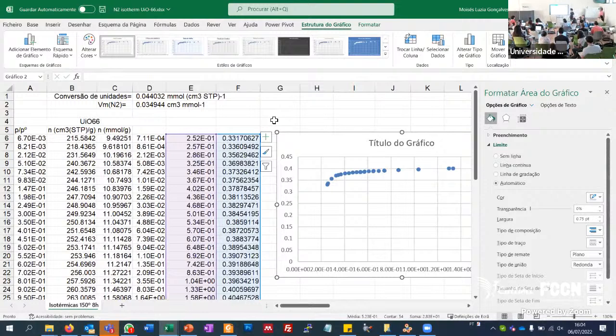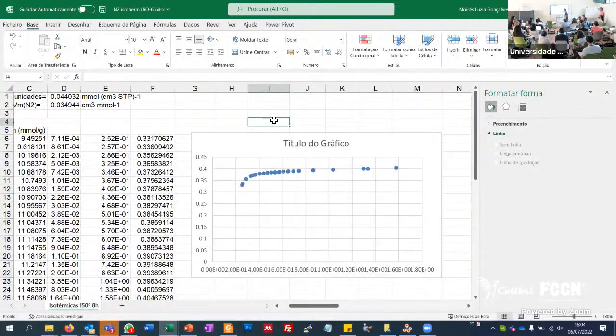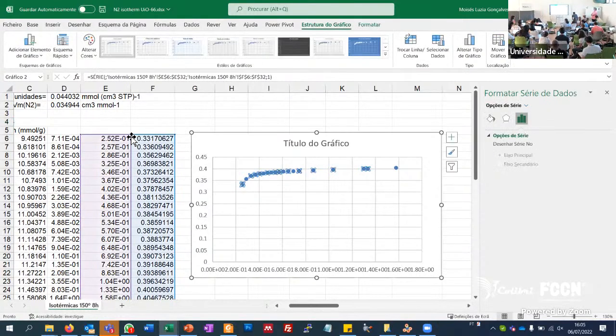Yeah? So what you need to do is to choose here some points around 0.4, slightly below 0.4 and slightly above 0.4. And why 0.4? Because this is the size of your nitrogen molecule, yeah? We are calculating for a monolayer. So if it is already well above, then it's not a monolayer thickness. It's not a thickness corresponding to a monolayer. Yeah? So if we use a value around here, let's see. Okay.